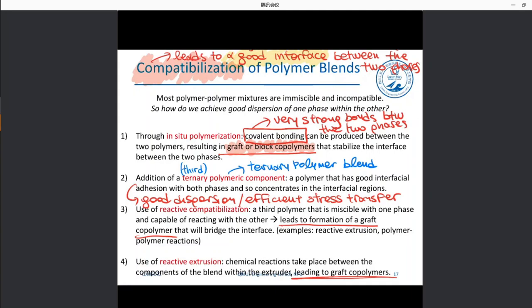We also use reactive compatibilization, a technique that can take place during mixing of the blends. Usually we use an extruder: we melt our polymers and mix them within the extruder. Again, we add a ternary polymer, a third polymer, which is miscible with one phase and capable of reacting with the other. Again, we have the formation of a graft copolymer. Reactive extrusion and reactive compatibilization are very similar.